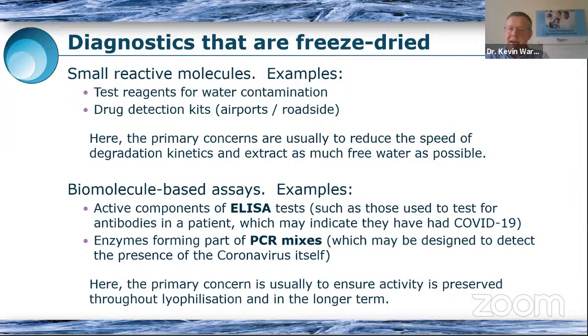And so we typically see ELISA tests, the enzyme-linked immunosorbent assay, where quite often it might be the enzyme or the antibody that needs to be stabilized by freeze drying. Or in terms of the PCR mixes, the polymerase chain reaction DNA-based diagnostics, it tends to be enzymes such as Taq polymerase that are the limiting factor to stability, and that we need to use freeze drying to stabilize them. Again, the primary concern is to remove water, but also ensuring that activity is retained throughout freeze drying and after freeze drying.